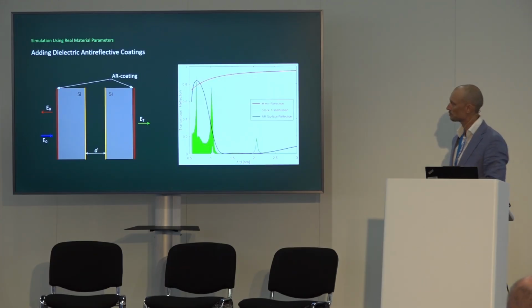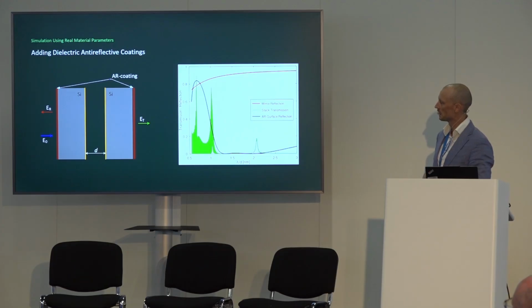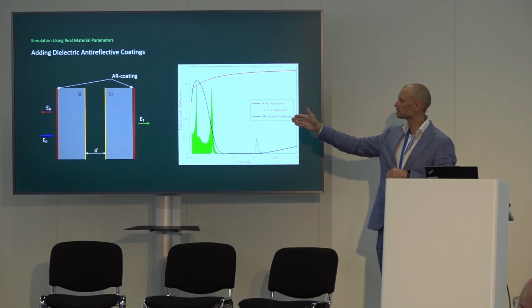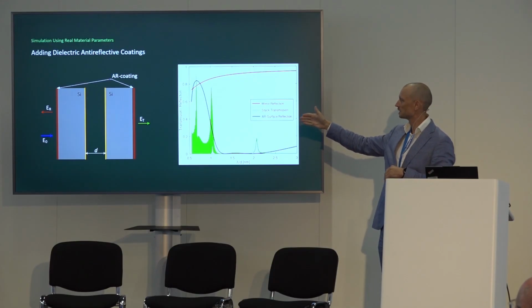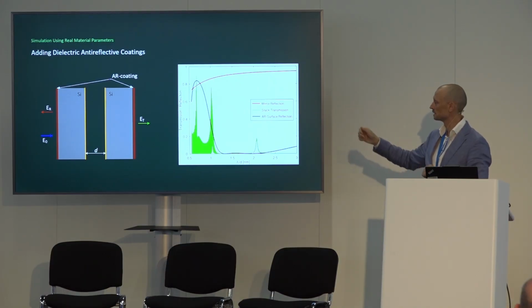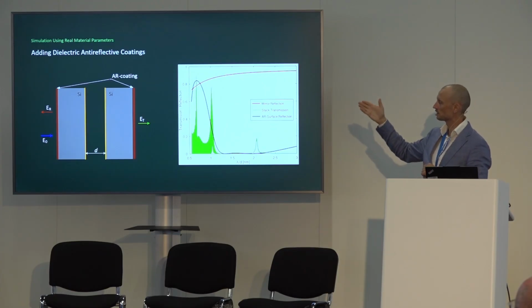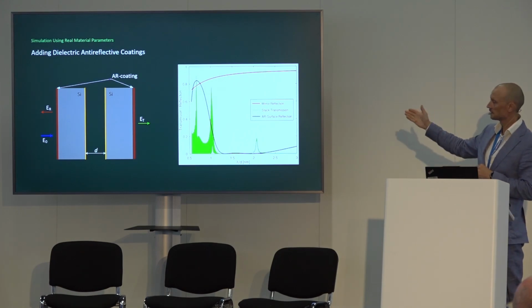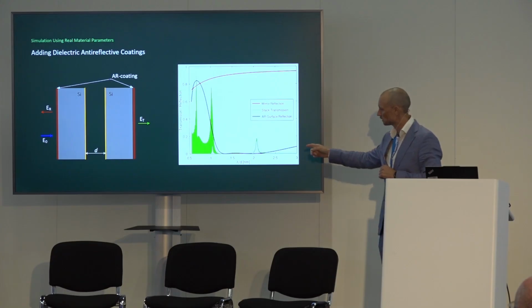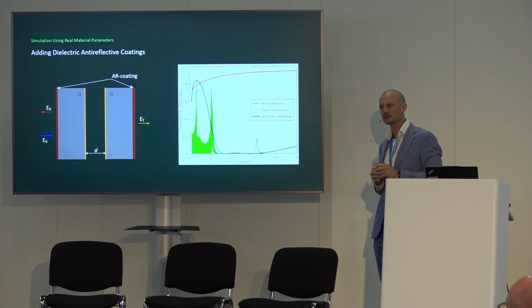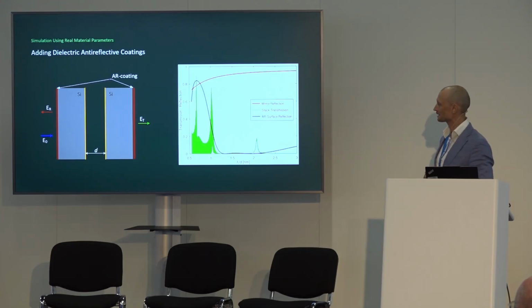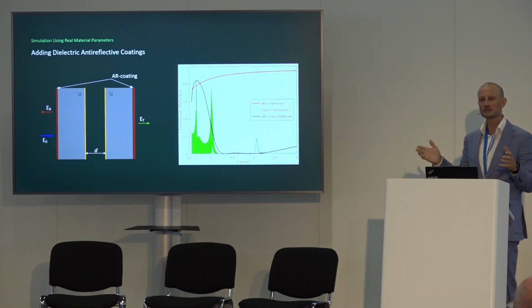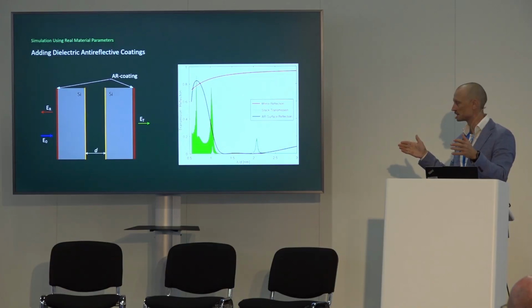So we do that. We introduce some anti-reflective coatings on the outer surfaces. And in this case, the light will come in from the left, won't see the first surface, and the first surface that it sees is the gold. Then the second surface is a second gold surface, and then exiting, there will be a new anti-reflective coating, so it won't see that either. So basically, what you're left with are two gold surfaces, two reflective surfaces, right? And in the plot, you see that, yes, at least for around 2 here, you do have a nice little peak, which is pretty clean. For the lower wavelengths, it doesn't really look as good, and that's because the anti-reflective coating is not really efficient over the entire region. It has a limited bandwidth.